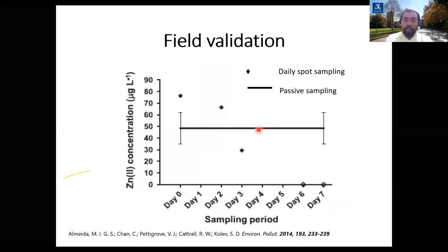A number of passive sampling devices were then deployed in a water system, and the results are compared to the daily spot sampling. As you can see here, the black line shows the time-weighted average concentration, or the average concentration over 7 days, obtained from the passive sampling device, which is in good agreement with the daily spot sampling.